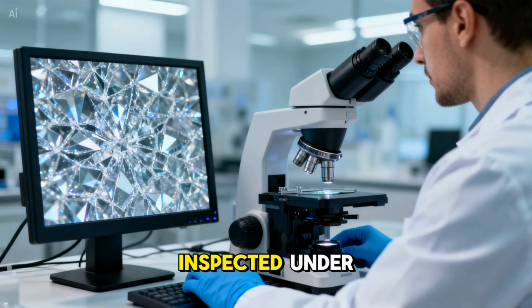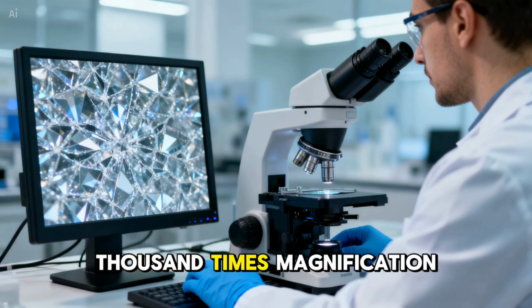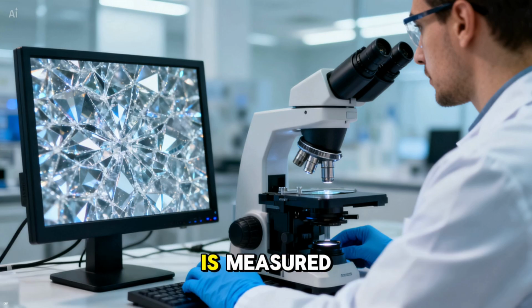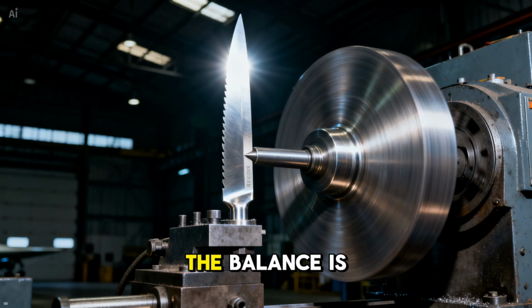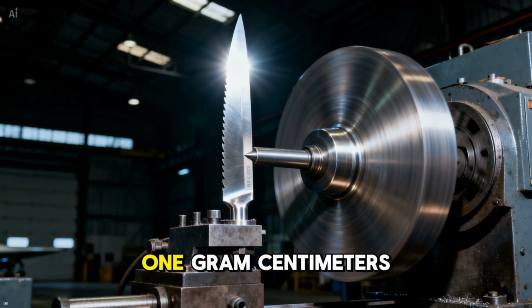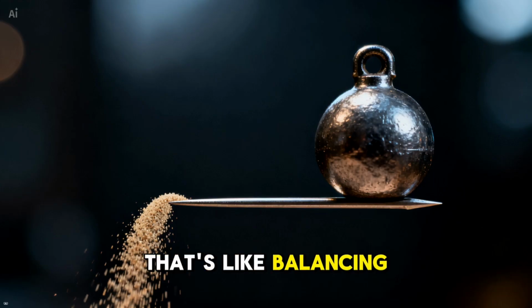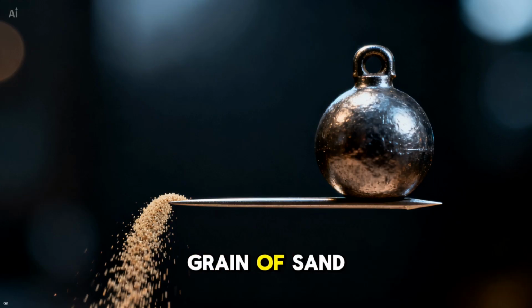The surface is inspected under microscopes at 1,000 times magnification. The coating thickness is measured with eddy current sensors. The balance is checked on a spin rig. The blade must be balanced to within 0.1 gram centimeters. That's like balancing a 20-pound weight with a single grain of sand.